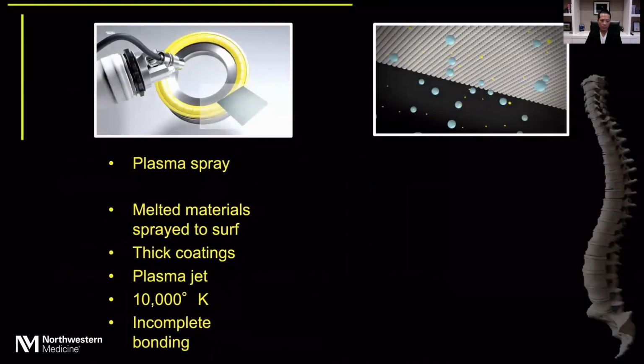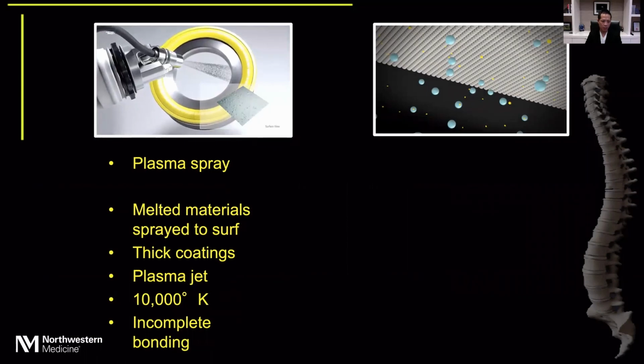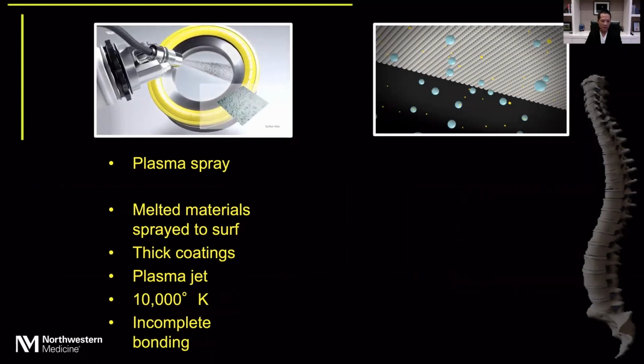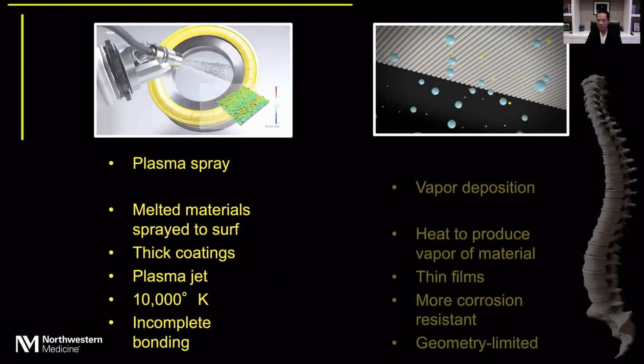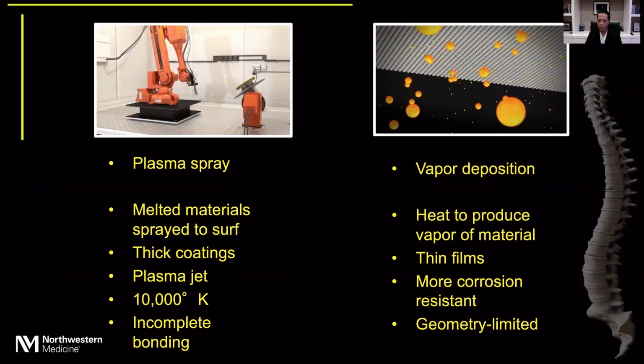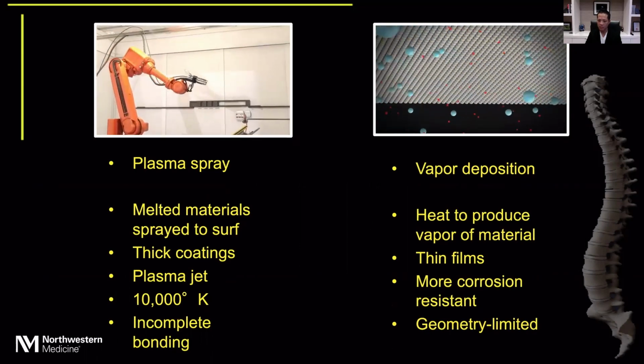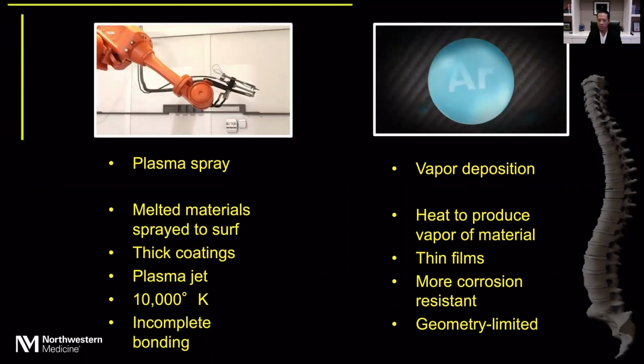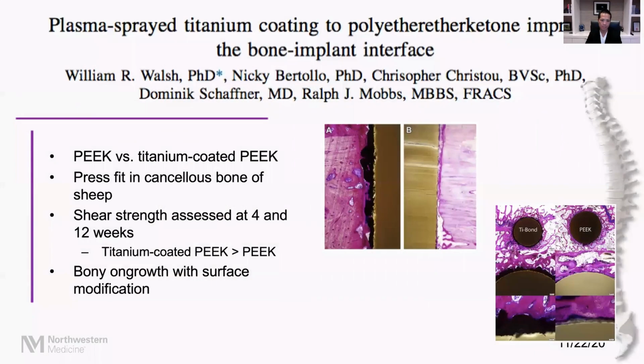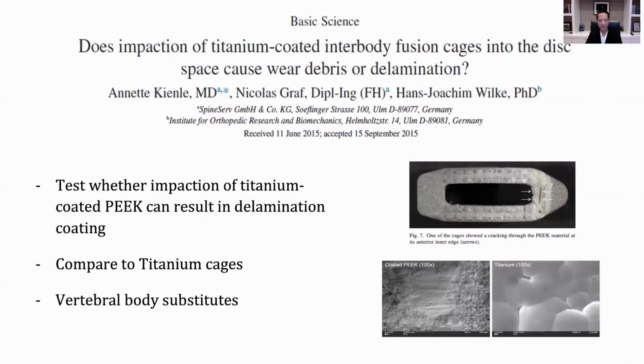There are two major ways in which materials can be coated, including plasma spraying, which melts materials sprayed to the surface, uses a plasma jet at high temperatures, but there is incomplete bonding. Vapor deposition has more of a complete bonding process, but it uses thin films, is more corrosion resistant, but is somewhat limited in the geometry of the structure that can be coated. We know that if you coat something like PEEK with titanium, you should get better shear strength and better osseointegration when compared to PEEK alone. But we also know that coating these materials, because of the incomplete bonding, can lead to a delamination of this coating when we insert the cages under friction, and this can be seen with this in vitro study.